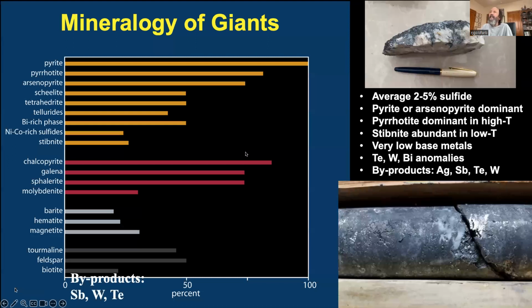If we look at the mineralogy of orogenic gold, again, I said it's generally 2 to 5% sulfide. It's generally pyrite, pyrrhotite, or arsenopyrite present in all of these. Pyrite is dominant, especially in Precambrian deposits or granite-hosted deposits. Arsenopyrite tends to be dominant in more sedimentary Phanerozoic deposits. Pyrrhotite tends to be dominant in the higher temperature orogenic gold deposits that form over 350 degrees.